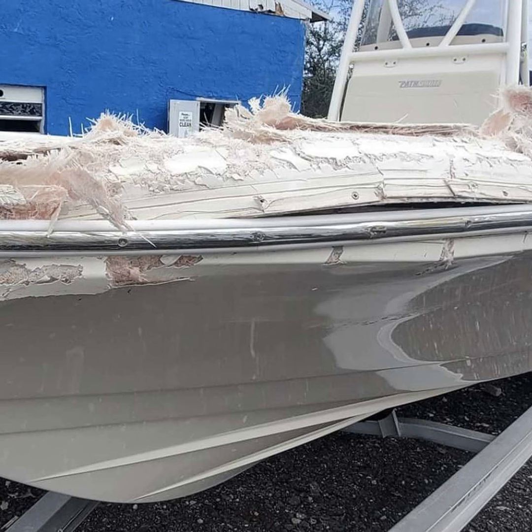If there's a way that you can take a look inside or at the back of whatever laminate you're assessing, I always highly recommend that. You need to do as thorough an investigation as you can, looking at the outside surface. If you're forced to make a determination only from that, you can do it. It's okay, because inevitably, if you start grinding, you're going to know the depth of the real damage. As soon as that gel coat's gone, it's very easy to see the amount of damage to the fiberglass laminate below it.